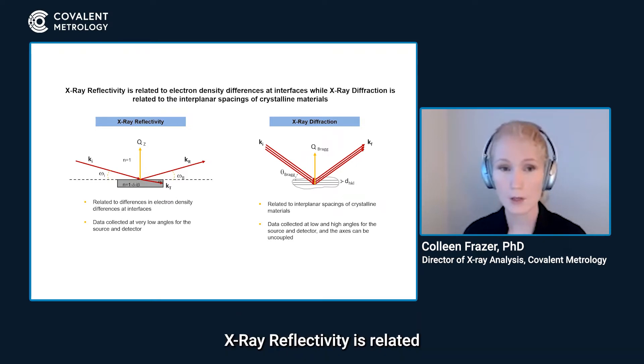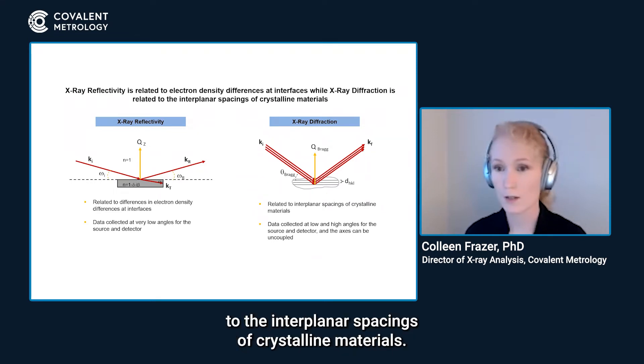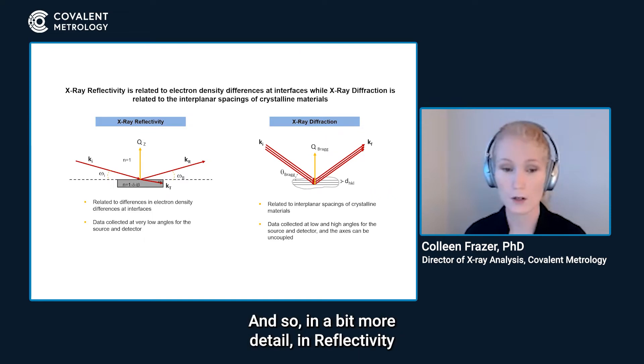So just to be clear, x-ray reflectivity is related to electron density differences at interfaces, while x-ray diffraction is related to the interplanar spacings of crystalline materials. And so in a bit more detail in reflectivity,